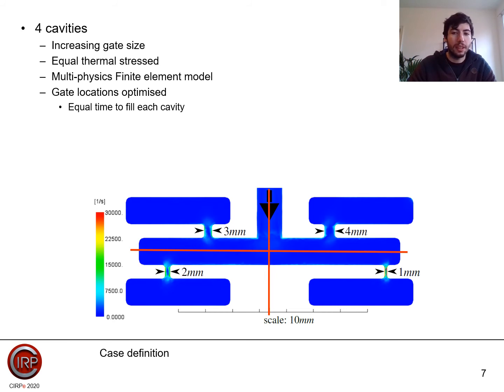In the design optimization, the cost function represents the difference in fill time, which is minimized. As such, the thermal loading of the mold material in each cavity should be equal, as the same heat exposure time is ensured. Note that the latter does not include the incoming flow. Also note that the sprue is still steel, and thus there is a large transition in thermal behavior where the flow enters the inserts.